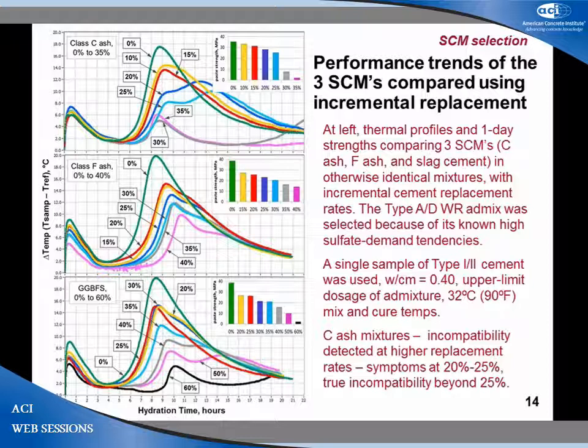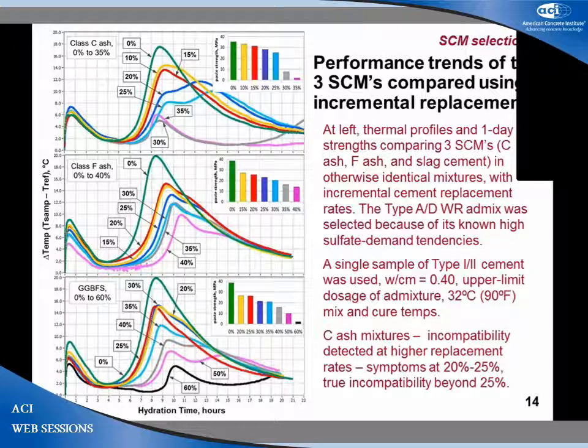And what we see in the case of this class F fly ash is pretty much the dilution type effects that we typically see through about 40% replacement. No tendency to misbehave. Slag cement or GGBFS, we can actually get on up to 50%, maybe even greater, with this aggressive admixture dose at a higher temperature and still have no particular issues with misbehavior. C ash, not so much the same. By the time we get a little past 25%, you see the shapes of those profiles are now beginning to change.